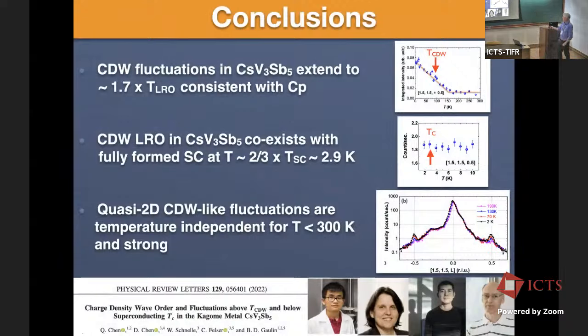And that is that there are strong CDW fluctuations in cesium vanadium antimonide that extend up to at least 1.7 times the 94 Kelvin transition to long-range order, and it's consistent with heat capacity. The CDW seems to coexist perfectly well. It doesn't go up, it doesn't go down, with superconductivity, at least at 2/3 of the superconducting transition temperature. And this might be even the elephant in the room, or something that's less expected and easy to understand, is that there seem to be these quasi-2-dimensional CDW fluctuations that are temperature independent, but they're present everywhere below 300 Kelvin.